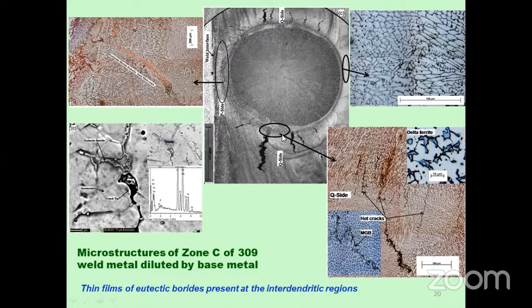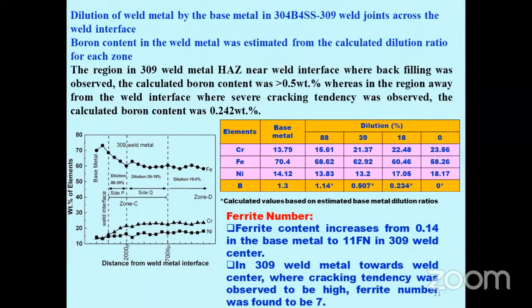So here there is no cracking. But in this region, cracking is very likely because there are only thin films of borides that are not enough to backfill. So this is the reason why we found cracking in the weld joints where we used the 309 electrodes for joining this borated stainless steel. So to calculate what the boron content is in this region where it was vulnerable to cracking, we did some SEM analysis and we have done this dilution study. From the dilution study, we have back calculated the boron content in this region. That is, the region where the dilution content is around 13 to 18% in this region.